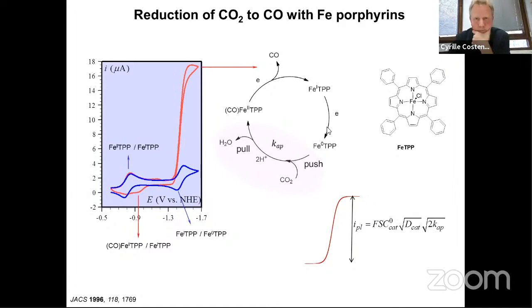And so the process here is that you generate iron 1 here and then iron 0, and then you have a kind of a push-pull process where CO2 binds to iron 0, which is very nucleophilic. And then in the presence of acid, you will pull on the oxygen and get water out, and you make iron 2 CO, which at this potential is immediately reduced to release CO. From the plateau current, we can get the kinetic information. So an apparent rate constant for this overall process here.